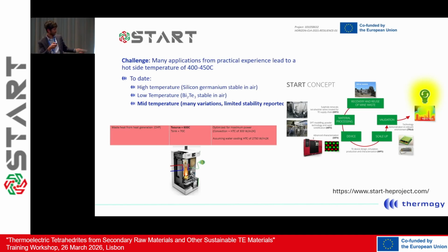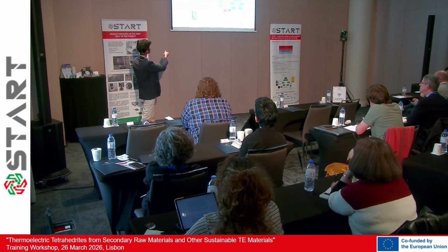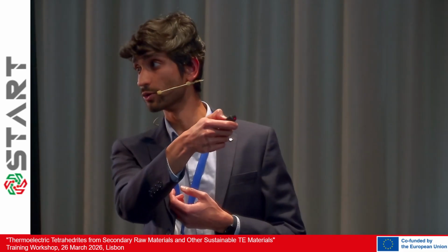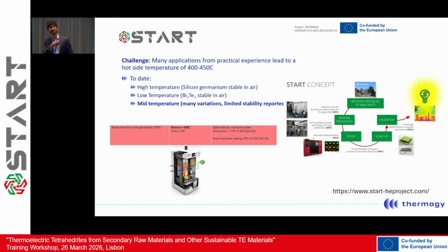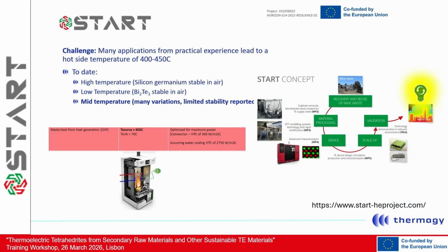Within the START project, as Alvise was saying, we start with a material which is basically mine waste material. The idea is to cycle it into something useful, and then finally get into a device which can be tested. The main motivation to get into this project was that, from our experience, we had a material which was stable at high temperatures. When you look at the market, most of you recognize there's a material stable at really low temperatures, though composed of elements that are not commonly available, yes, tellurium. But in the mid temperature range, from 250 up to 600 degrees centigrade, there was quite a big gap in the literature itself.